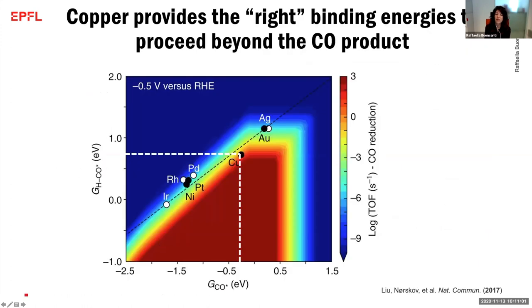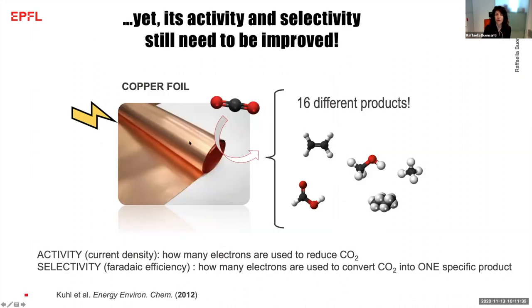Among different metals, copper is special because it has an intermediate binding energy towards these key intermediates, CO and CHO. Metals like silver and gold are highly selective to make CO because they don't bind CO too strongly. And so the reaction proceeds from CO2 to CO, and then eventually CO leaves the catalyst surface, so it cannot go farther. Other metals bind CO strongly, and so they get poisoned, and the reaction cannot proceed. So copper is special. At the same time, if we use a copper foil, we are going to produce 16 different products, so this will be a separation nightmare.